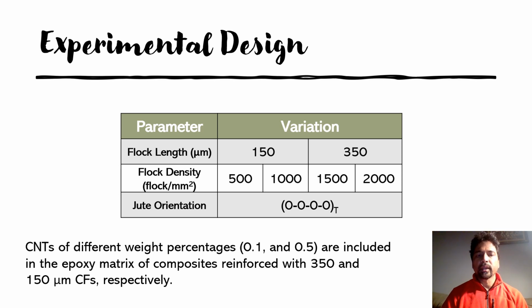In this study, we have 2 different weight fractions of carbon nanotubes, one for 350 microns, which is 0.1%, and 0.5% for the 150 microns carbon fiber composites. The reason we wanted to use 2 different weight fractions is because the 350 micron system provides a better conductive network compared to the 150 system, as we saw in the previous presentations.